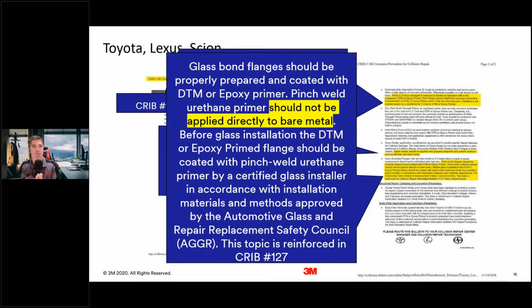And I point this one out because Toyota has identified that all glass bonded flanges need to be epoxy primed. They cannot be left bare metal, and even if a manufacturer has a direct to metal pinch weld urethane primer, Toyota said, nope, you can't use it. You have to be putting it over a 2K epoxy primer, even if the product you're using to glue the window back in says that it's a direct to metal product. So again, the OEM here is superseding the product maker's recommendations, and the product maker should have their products work in alignment with this type of procedure.